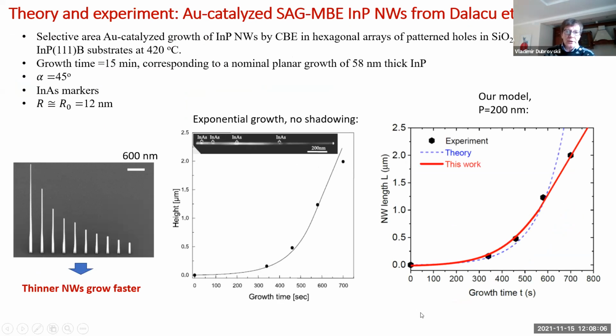So I have then compared this with the results given in this paper. This was CBE growth of indium phosphide at 420 degrees. They grew nanowires from different size droplets, and what they saw is that thin nanowires were grown longer, which is also within the model. But then in one nanowire, which was not tapered, they introduced markers in order to measure the height or the length versus growth time. And that was the exponential fit. You see? And no shadowing was taken into account.